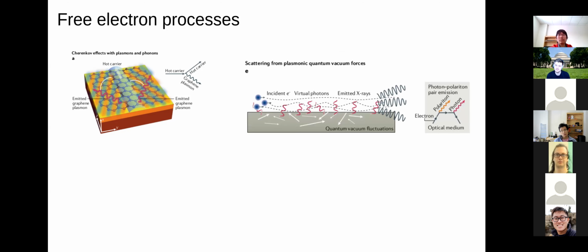Something that's at second order instead of first order would be taking an electron beam, shooting it above the surface of a material like graphene or something else that has confined polaritons. It really doesn't matter what it is. And then looking at two photon spontaneous emission processes from this free electron, so that the electron emits two things. One of them is something like the polariton into the surface, so it could be a plasmon. And then the other thing would be a higher frequency photon into free space. And so you would have a pair generation of photons where one of them is like an infrared plasmon, and the other one is like an ultraviolet frequency photon that goes off into the distance.